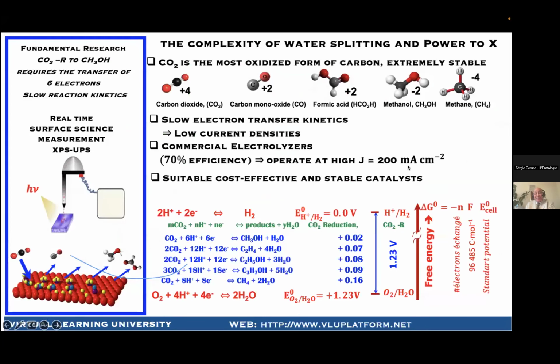Okay. There is a complexity for the water splitting. You can see, for example, here, CO2 is the most oxidized form of carbon, and it's extremely stable. Here, the oxidation degree is +4, and here for CO it is +2, and for formic acid +2, for methanol -2, and methane is -4. And therefore, depending on this oxidation degree, you can have more or less difficulty to reduce the compound. And you see for carbon dioxide it is very difficult. So you have slow electron transfer kinetics. That's one of the problems. That's why we always need a catalyst.